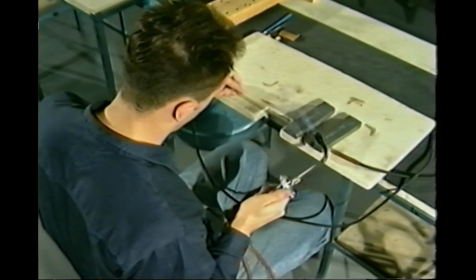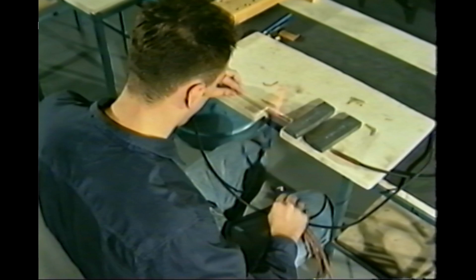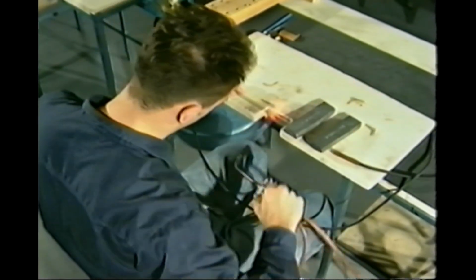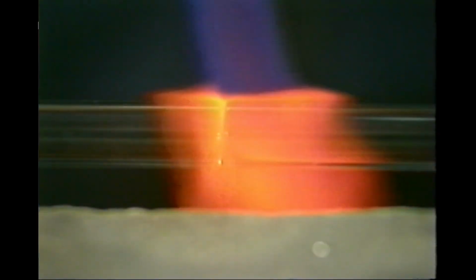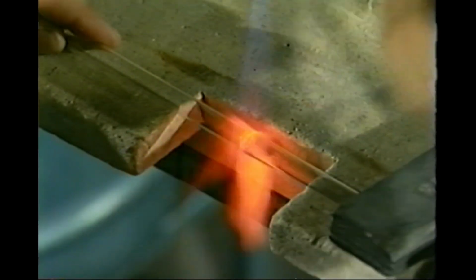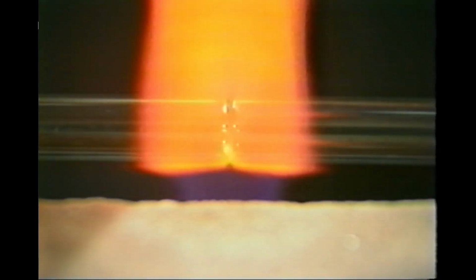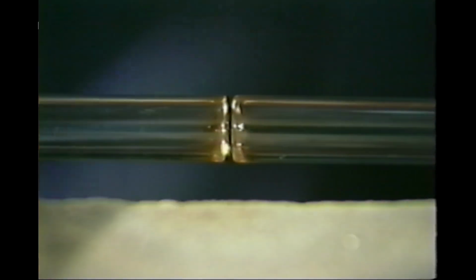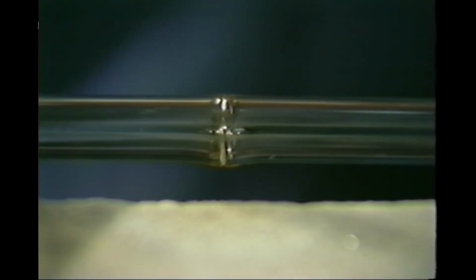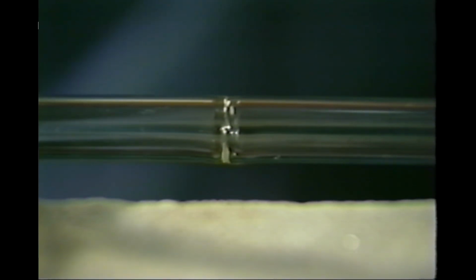Adjust the flame on the hand torch down to a wide, fairly strong flame. Keeping the flame at right angles to the tubes, begin melting the two open ends, rotating the hand torch at speed back and forth to effect equal heating right around the two open ends. When the two open ends melt to a dull red heat, remove the flame. Touch gently together the two open ends. Give one gentle blow and at the same time pull out slightly the left-hand tube. This blow and pull action will remove some of the ridges and folds pushed into the joint by the initial contact.